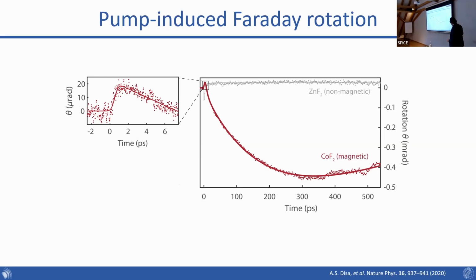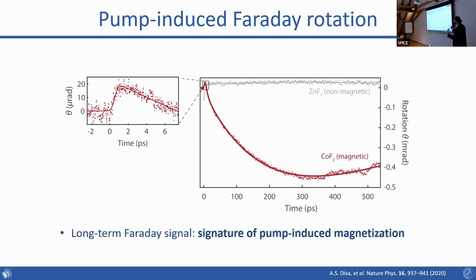For example, we carried out the same experiment on zinc fluoride, which is non-magnetic, but has basically the same phonon spectrum. And you can see that you have this coherent artifact, but no real long-term signal like this. We also carried out a circular dichroism experiment, which shows the same behavior in cobalt fluoride. So this long-term signal is a signature of this pump-induced magnetization.